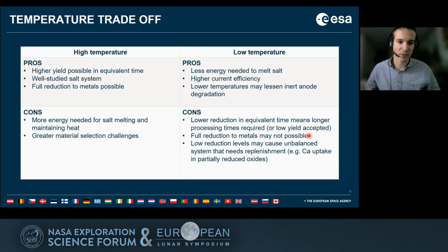So if we can make a small trade-off table from this result: at higher temperatures, so far we feel that we still have higher yield, and this is still a well-studied system. All terrestrial systems are still working at 950 degrees. But as a con, of course, we still need to solve the material challenge regarding the anode and the reactor, and of course it's more energy for melting the salt and then maintaining the temperature of the system.